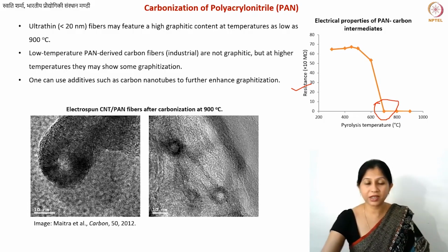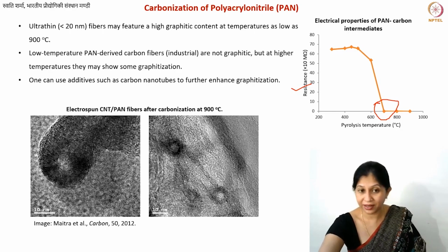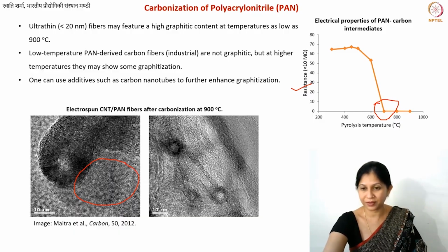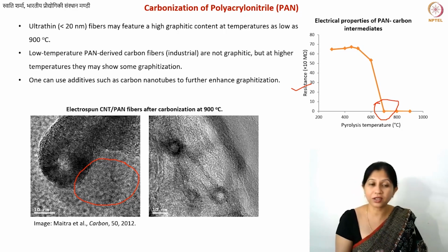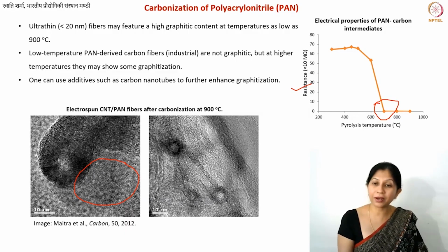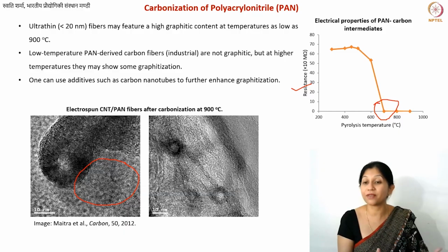What is the advantage of this entire process? I don't know if it is clear in these pictures, but if you look over here, the regions that are close to the nanotubes show more graphitization because of this templating effect. That is what you can do to improve the graphitization. We also see this in the transmission electron microscope images, and we can also do electrical conductivity measurements. Typically, if you have higher graphitic content, you will have higher electrical conductivity. So depending upon your application, for sensing applications or for gaining more mechanical strength, you can test different properties. What do you want from your fibers?